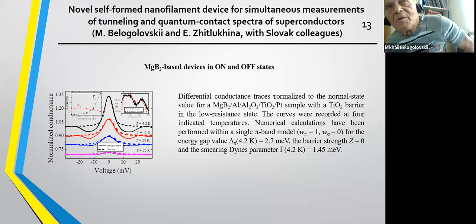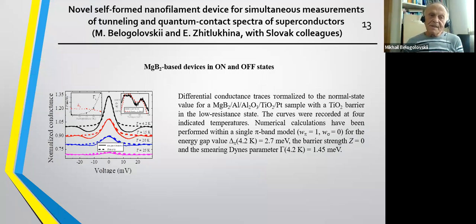So it would be useful and interesting to create such a system where you are able to switch between two regimes. The idea was to use an insulating layer between the studied superconductor, which was in this case magnesium diboride, and the counter electrode, which was platinum, and to create it with titanium dioxide, which is known as a material that switches between high and low resistances after applying a voltage bias pulse. So it is known as the electroresistive effect.